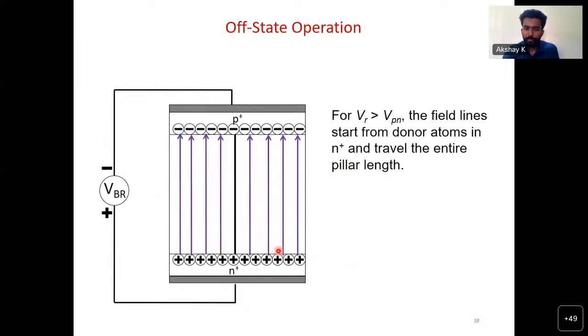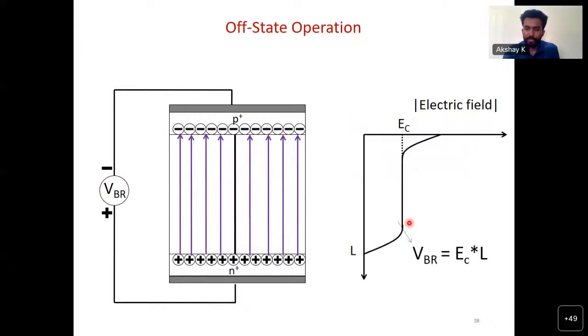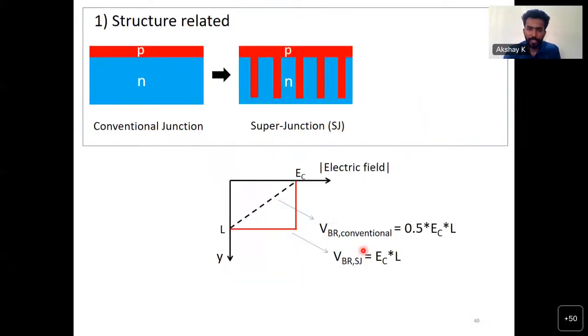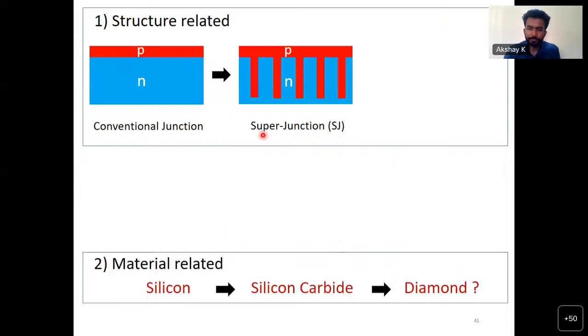So for any additional voltage, the electric field lines coming from this positive charge will be able to travel the entire length of the pillar and get terminated only on the negative ions here. Okay, so that is why you get a very straight kind of electric field profile. Only if these lines get terminated on any leftover charge here, there will be a slope. If there is nothing to terminate these field lines, there won't be any slope. So that's why you have approximately a rectangular kind of distribution, and hence a high breakdown voltage for superjunctions.